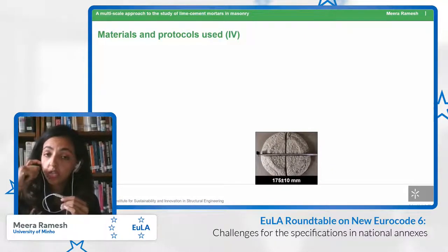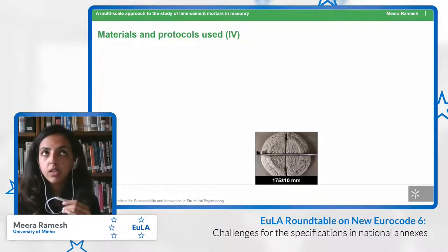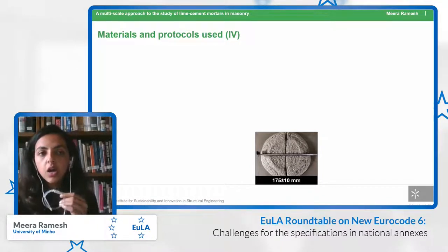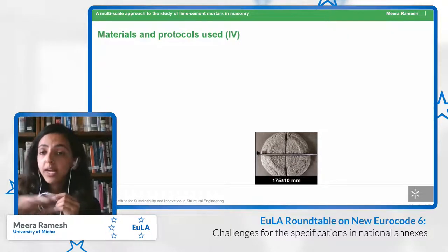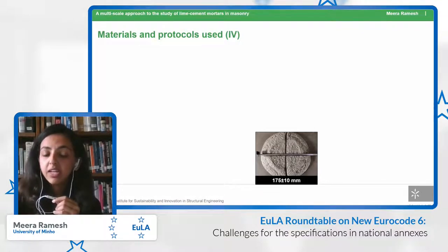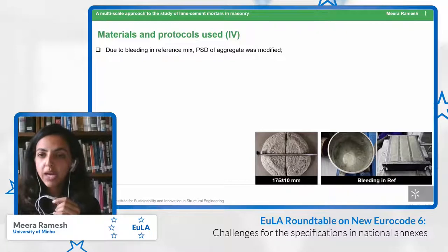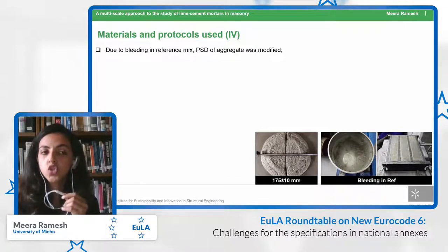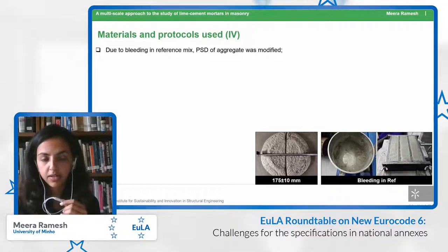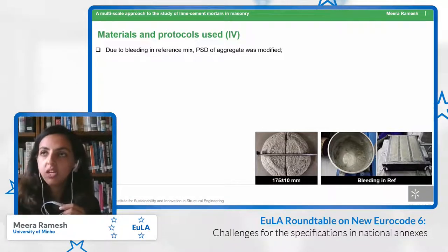So as I mentioned, the flow table value or workability was a very important parameter for us because we wanted the mixes to be actually used on field such that the masons would be happy working with them. And so this was very important to us. However, what we realized was when we removed lime from the mix and we wanted a reference cement mix, we were having issues in attaining this workability. Essentially, what happened was bleeding. So every time we would jolt the mix, some amount of water would be expelled. And we tried various things. We even tried using a plasticizer, but nothing seemed to work in the absence of lime.